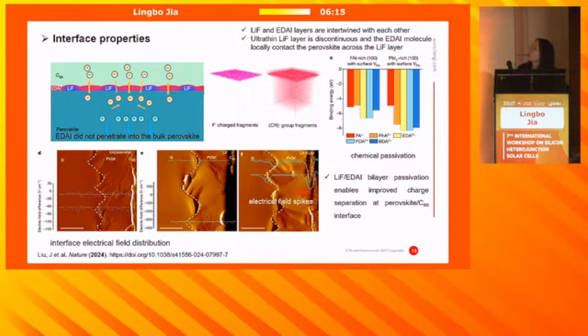And also the ultra-thin lithium fluoride layer is discontinuous, and the EDAI molecules locally contact the perovskite across the lithium fluoride layer. So the EDAI materials can form a point contact between perovskite films and carbon-60 to passivate the defects of perovskite films, and also can provide another path to facilitate the charge transfer.